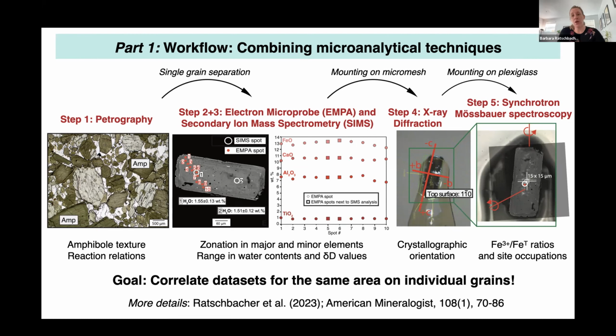So in the next step, we then remove those amphibole grains from the epoxy mount and mount them on a micromesh for X-ray diffraction. And that's a really crucial step prior to taking the individual amphiboles for synchrotron Mössbauer spectroscopy, because with XRD, we can determine the crystallographic orientation of each individual grain. And you will see in a moment why this is really important. But then the last and final step is to take the individual amphiboles, mount them on a plexiglass slide, and analyze them for their ferric over total iron content at beamline 3, using synchrotron Mössbauer spectroscopy.